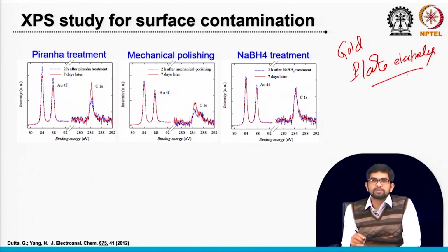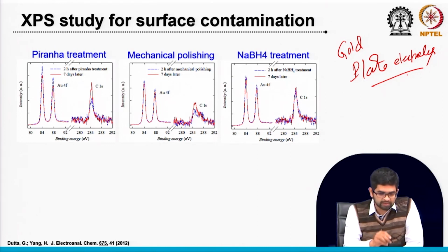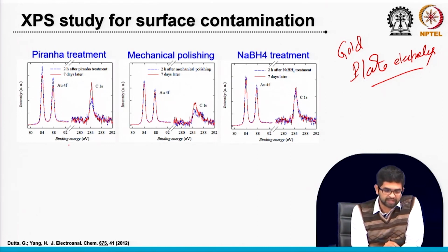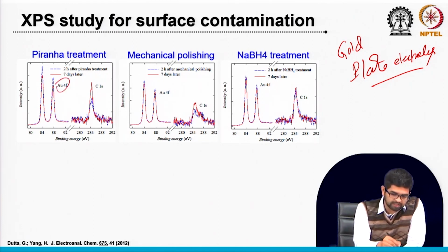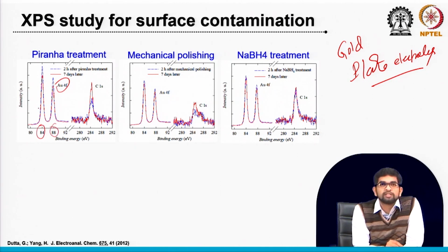Okay, if you see all the gold plate electrode just after this piranha pre-treatment, here we studied X-ray photoelectron spectroscopy, XPS. You see we generally get the gold peaks in this region, two peaks around 84 and 88. So in these two regions we get the gold peak, and the carbon peak around this region.